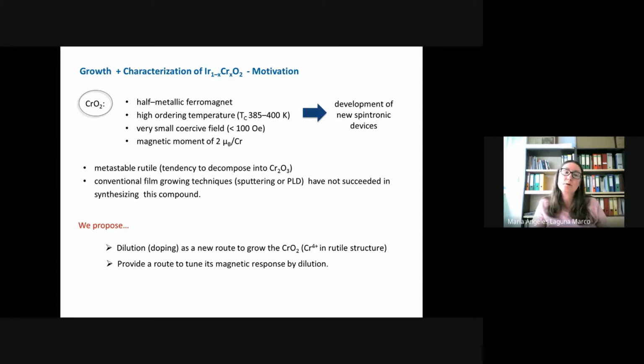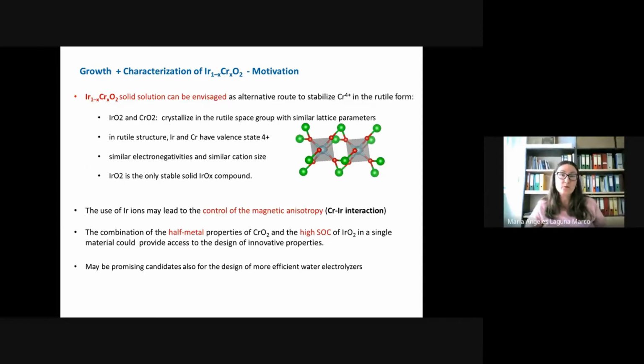Here, we propose diluting or doping as a new route to stabilize the chromium 4+ ion in the rutile structure. This route could prove to be also useful to tune the magnetic response. It is to be noted that chemical doping has been barely and only recently explored. Therefore, within this context, in this work, the growth of iridium-doped chromium dioxide is explored.